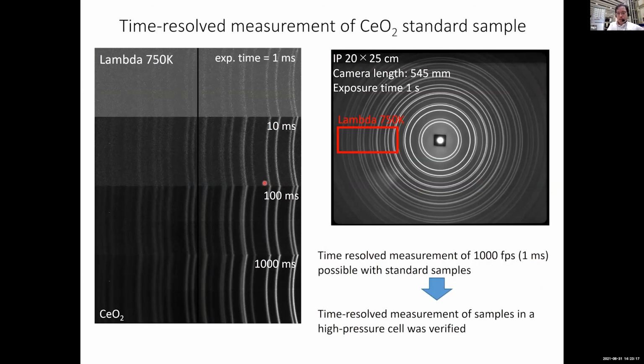First I tested the time resolved measurement using a cerium oxide standard sample and confirmed the diffraction line could be observed even with an exposure time of 1 millisecond, and that the signal noise ratio was enough for analysis with an exposure time of about 100 milliseconds. This is from the Lambda detector, and this is the imaging plate, the entire Debye ring using a pink beam.